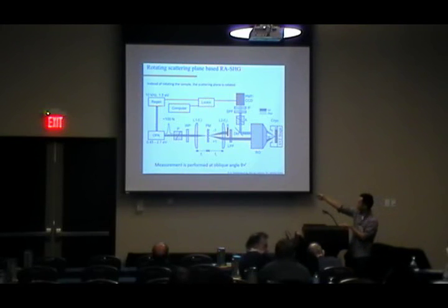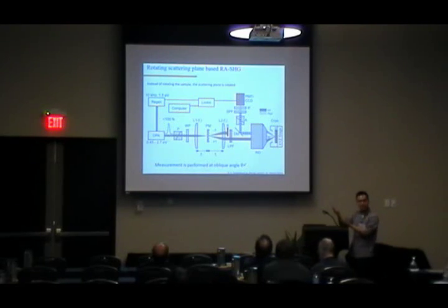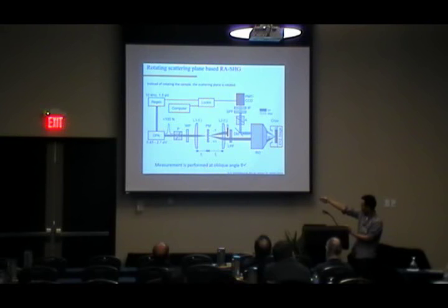We start off with what's called a regeneratively amplified Ti:sapphire laser operating at 1.5 electron volts and a 10 kilohertz repetition rate. That seeds an optical parametric amplifier that enables you to tune the central wavelength of those pulses between visible and near infrared in our case. That selected wavelength gets polarization filtered, goes through a wave plate, and gets focused on this critical optic called the phase mask, which is a diffraction grating in transmission.